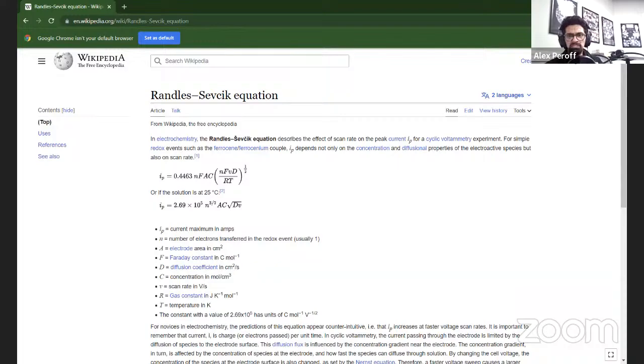But I hope that is enough of an expansion, Ramachandra, on the Randles-Sevcik equation. It's a mathematical equation. It just relates that peak current to all of those values. It's mostly used when you know what the area of your electrode is and you know the concentration. You can usually determine a diffusion coefficient, and people will do scan rate dependent tests, correcting for the background current because the background current changes, and then using those peak currents, doing a linear regression to then determine what the diffusion coefficient of your molecular species is. So I hope that was helpful.